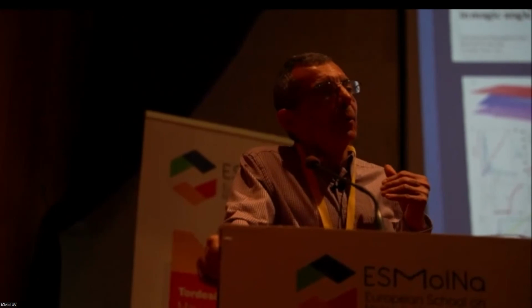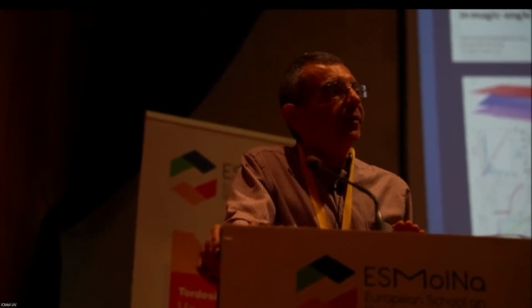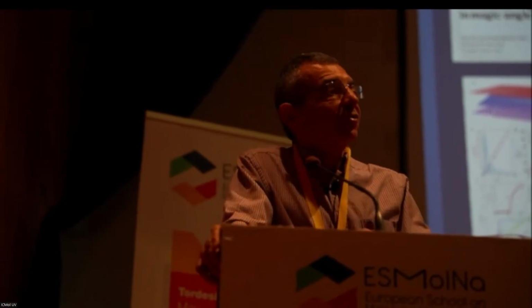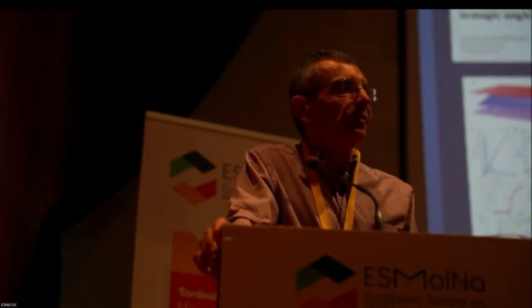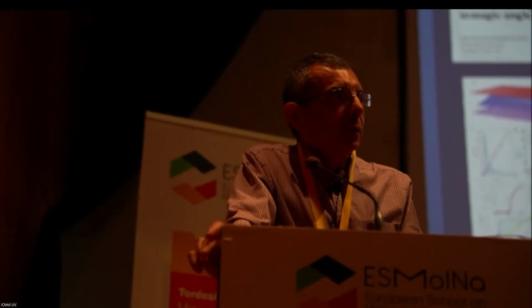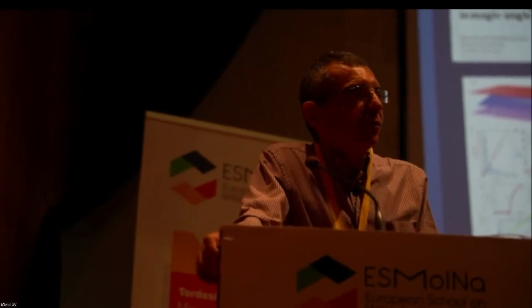Then, well, experimentally, I suppose that it is in this way, but in theory, you can also investigate the situation in which it's not one eclipsed layer on the other one, but you can shift one with respect to the other one. Good point. What happens in this case? Okay. If you ask, it depends who. If you look at the lattice level, there is a small difference, but it is assumed, and there are good theoretical arguments for that, that at very small angles, where you have a large moire unit cell, that doesn't play a major role. Just a shift, keeping the angle fixed. So two samples with the same rotation, but some extra shift, should behave in very similar ways and have similar flat bands. That's the theoretical analysis, but it neglects spin-orbit coupling at the lattice scale, which nobody knows what will do. So there are still unanswered questions in that respect as well.